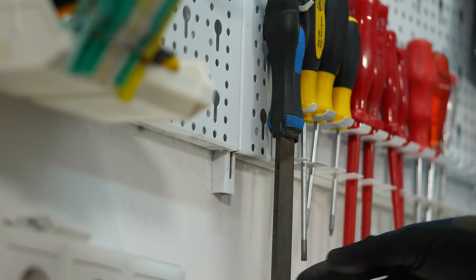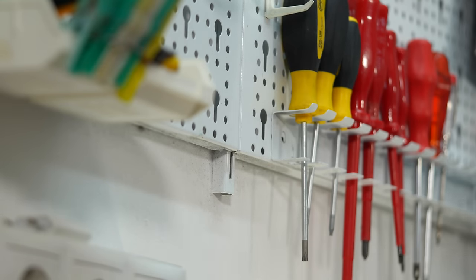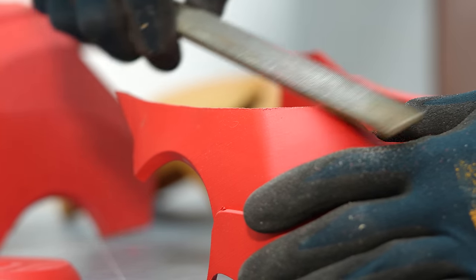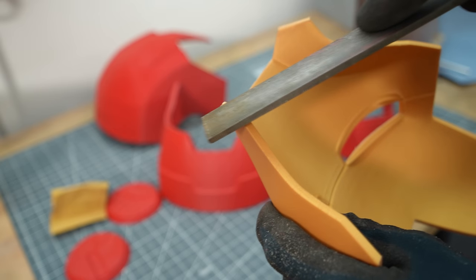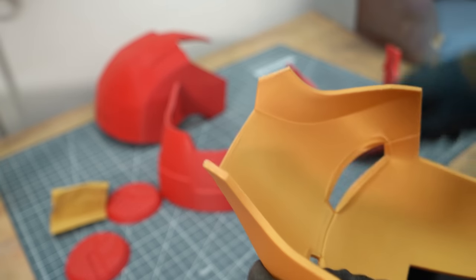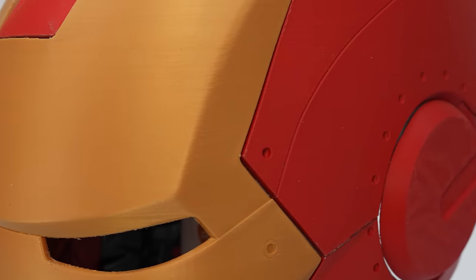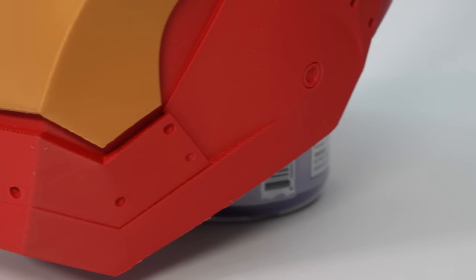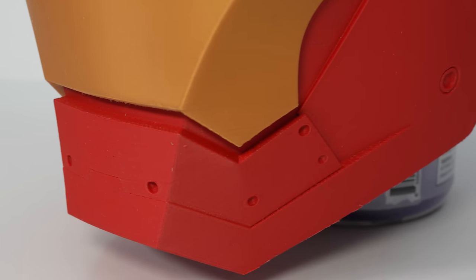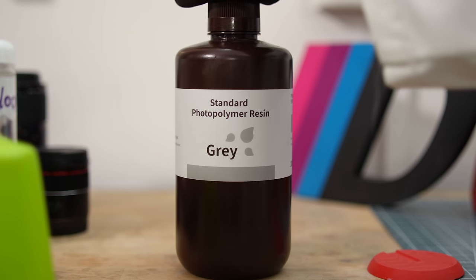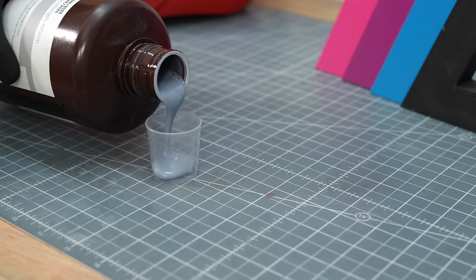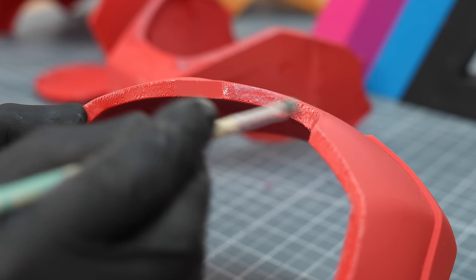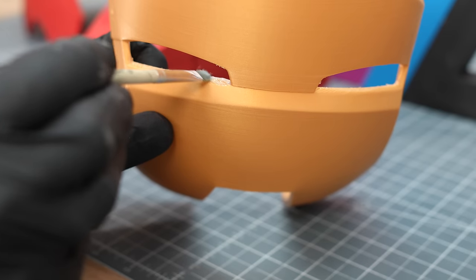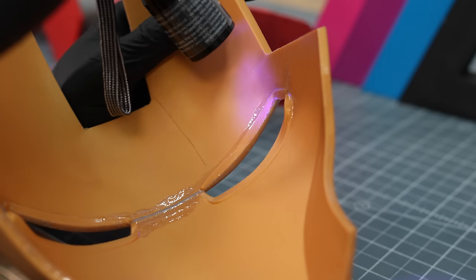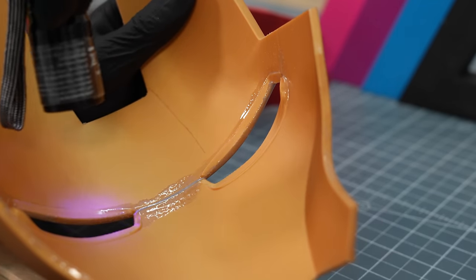There are now two crucial steps. The first one is deburring and filing all pieces to fit and roughly sanding them. This is an FDM printed helmet with infill. No FDM print is watertight and I definitely don't want electrolyte to enter the helmet. That's why I seal all areas and potentially open seams with resin. And I use old 3D print resin for this. Simply brush the respective areas and cure them with a UV flashlight.